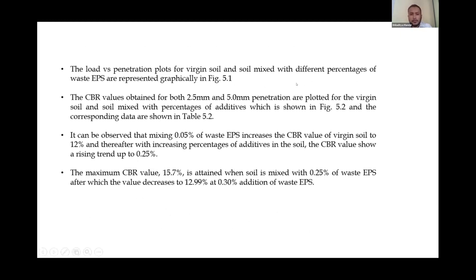Now the load versus penetration plots for virgin soil and the mix ratios have also been presented later, which I'll show you in a moment. It can be observed that at 0.05% waste EPS, when we add our first inclusion of waste EPS with the dry weight of soil, the value of CBR shot up to 12%. That is quite a high increment in CBR value. And this trend was continuously observed till we reached the 0.25% mix. The maximum CBR value was obtained at this 0.25% waste EPS mix. And after that, when we added 0.30%, we saw that this value started to decrease.